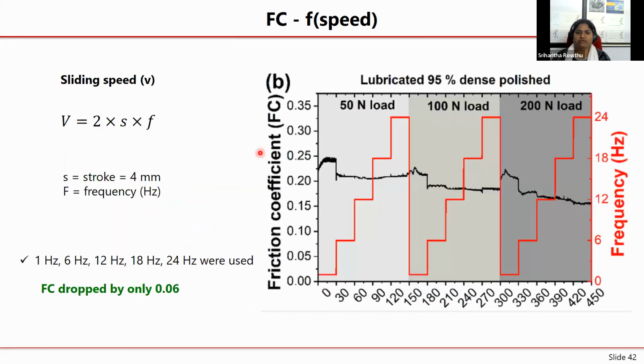Then we also conducted tests where we change the sliding speed. In the case of reciprocating sliding, speed is nothing but 2 times your stroke times frequency. So we can play with the frequency and change it from 1 hertz all the way to 24 hertz. That is what you see as these steps. So this step means it's at 1 hertz. You have to read the right-hand side, and then later on 6 hertz, then 12, 18 and 24.